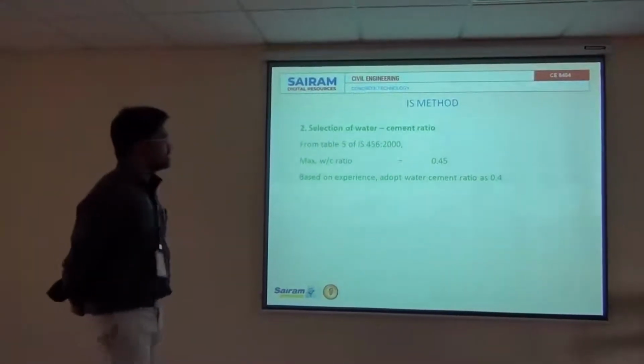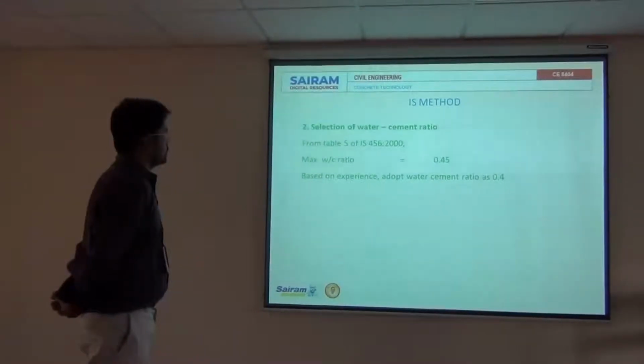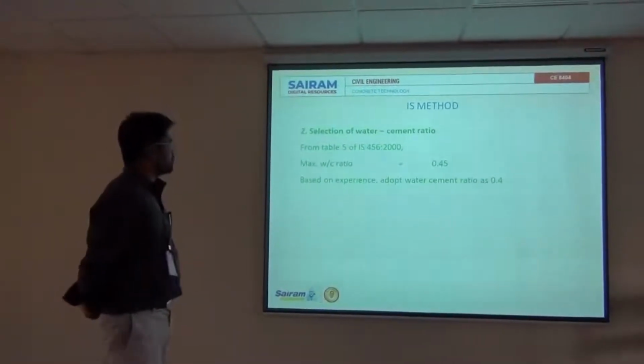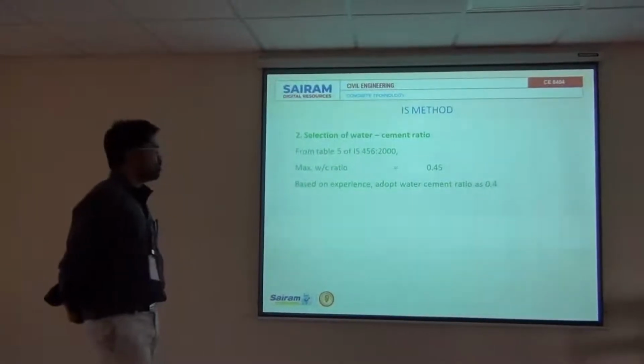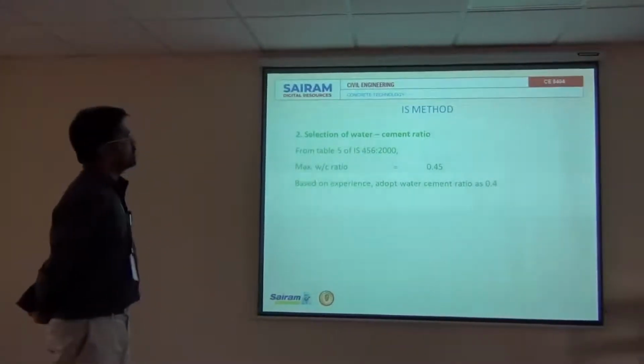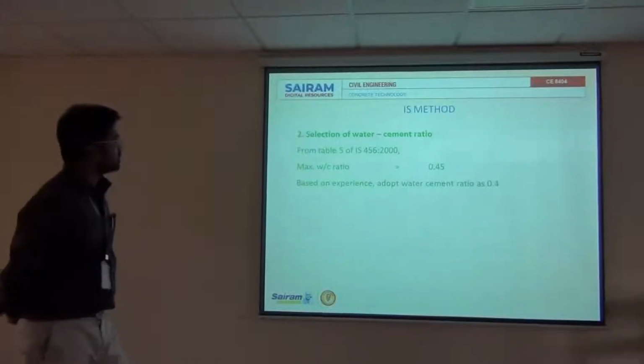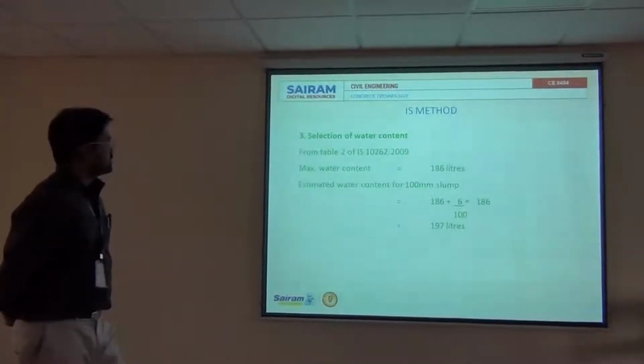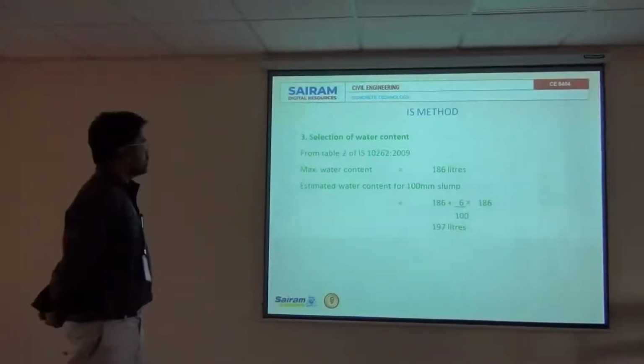The given exposure condition is severe. For severe exposure condition, you refer to table 5 of IS 456:2000, and you get maximum water cement ratio 0.45. In that case, I select water cement ratio 0.4. Then selection of water content, referring to the code book.